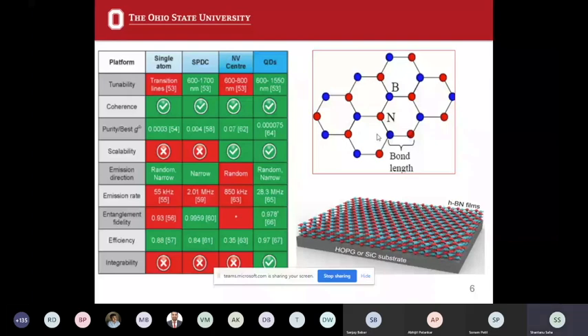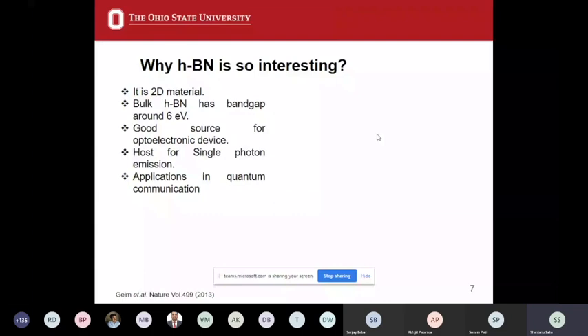So why is hBN so interesting? hBN is fascinating because it can emit in both visible and UV regions. It has very high brightness and controllability of emission. Point defects in hBN are responsible for single photon emission, but whether it is nitrogen vacancy or boron vacancy has not yet been proved so far. Every day you'll find a new paper and they are arguing with each other. Recently, I found one paper which suggests that carbon vacancy might be the reason for getting single photon emission, but it is still under debate and no one has proved it experimentally. Until some group experimentally proves a result, the debate will continue.